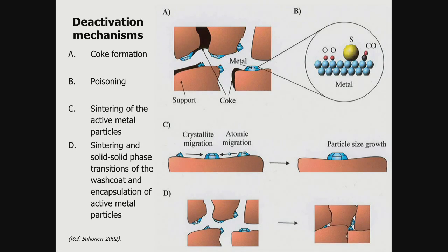Okay, but we designed that process and it works, and we've been using it for the best part of 50 years. And then what do we do to get our lovely precious catalyst at £10,000 to £20,000 a tonne back, which has got a lovely surface area and it's very reactive and we love it dearly? What do we do to it? We stick it in a regenerator. The regenerator works between 750 to 800 degrees C. That's 250 degrees above the process temperature that we put it in at, and we put it in steam. So we put it in a very energetic kettle and we regenerate it, and then we put it back into a fluidized bed.